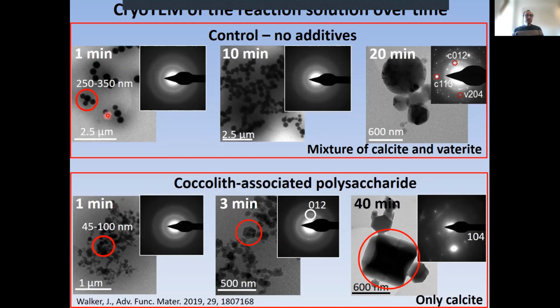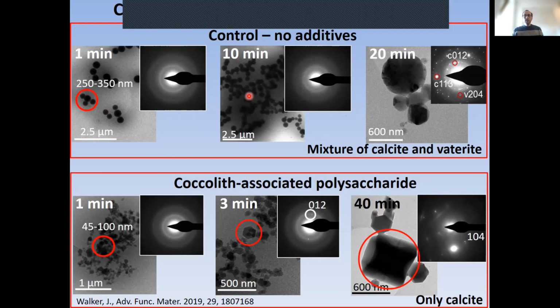And what you observe is the formation of these spherical particles. So this is amorphous calcium carbonate. It's not crystalline yet. It's known to form as a precursor to calcite. And then over time, it crystallizes into vaterite and calcite, which is what we expected. And the proportion between the two is pretty much 50-50. When we added polysaccharide in the solution, what we had was very quickly the formation of calcite crystals, and only calcite crystals. 100% of the material that we got out of this was calcite, even though we were under conditions that were favoring the formation of vaterite as well.